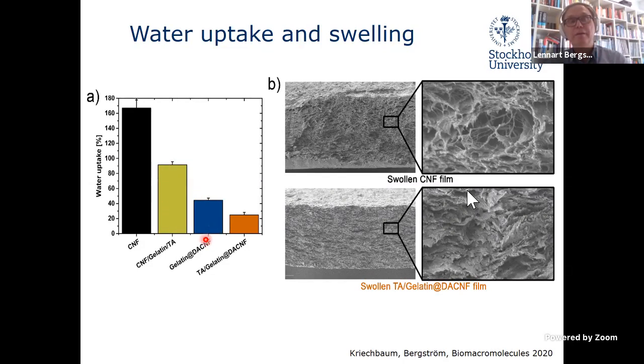If we graft gelatin onto CNF, we reduce the water uptake even more. And if we precipitate this material with tannic acid - the tannic acid precipitated gelatin grafted onto CNF - you can see that the water uptake is down to a little more than 20%. So it's a significant decrease of the water uptake.